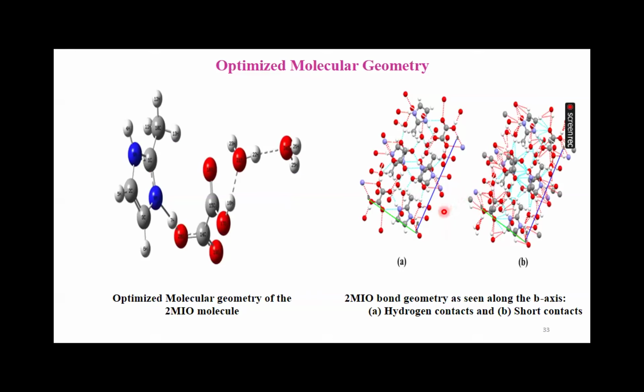The molecular structure interactions between DFT and XRD were determined in the gaseous state. Both the methods are in good agreement with each other, such that they give results consistent with X-ray diffraction and theoretical geometric parameters. HOMO-LUMO analysis.